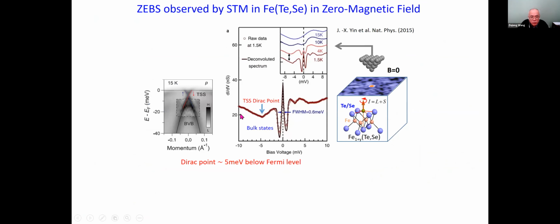Here I show this again. I want to actually make a point. If you look at Shu Han's data, this is a V-shaped density of states at -5 meV. And that is completely consistent with ARPES having a Dirac crossing about 5 millivolts below the Fermi level.